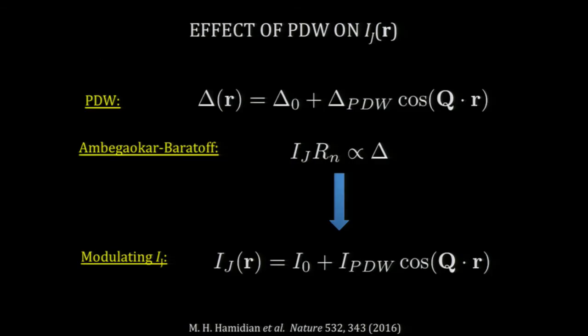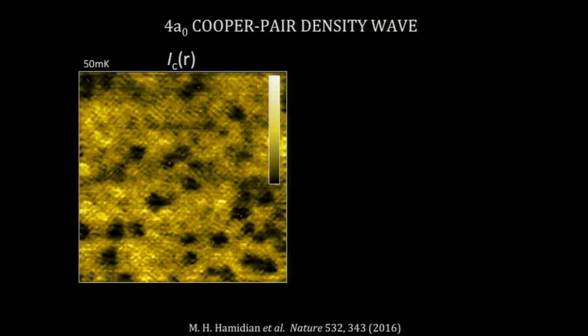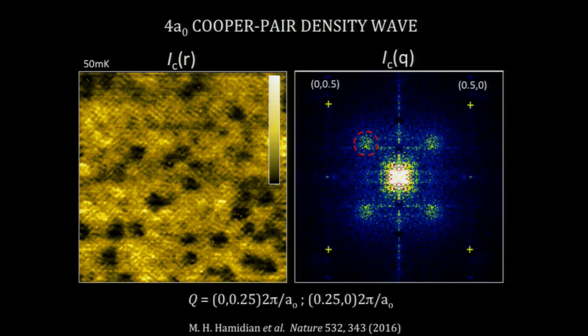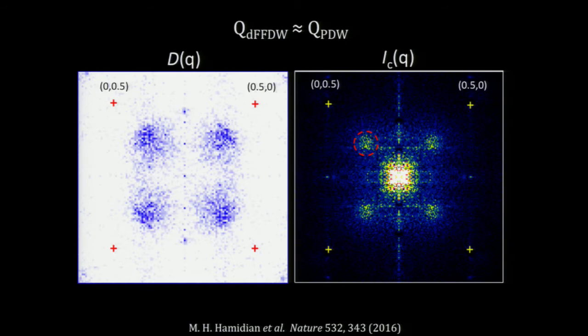Now, if there were a pair density wave in the system, what would you expect? Well, if the order parameter had a uniform component and then a modulating component, then there is this Ambegaokar-Baratoff relationship which relates the critical current to delta. That would tell you that the critical current should also then have a modulating component to it as well. Well, you can already see by eye there's some modulations in the system, but we always like to take Fourier transforms. And when you take a Fourier transform, it becomes very obvious that there are 4 peaks which represent a 4-unit cell modulation in both directions in this modulated superfluid. And here's that image I showed you earlier on. This was the modulation of the electronic structure measured by STM in those ladder patterns. It turns out that the Q vector, the modulation wave vector of this object and this object, are very, very close.